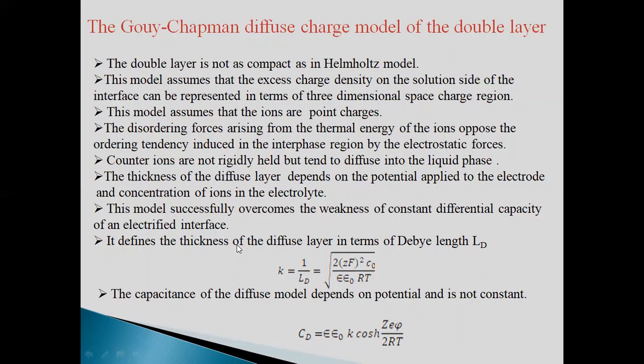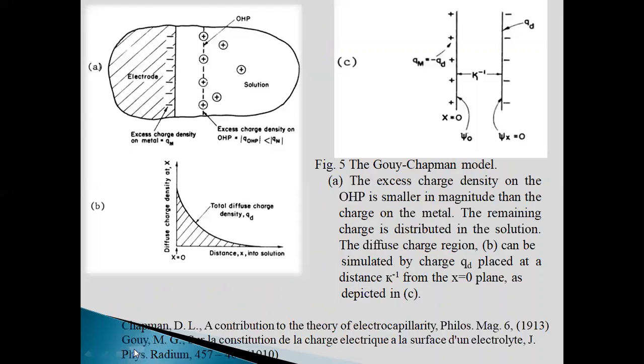So, as shown here, it also tells us about the thickness of the diffuse layer formed in this model, and it is given by the length kappa, which depends on the concentration of ions. So the capacitance is not independent of potential and the concentration of ions according to the Gouy-Chapman model. As shown here, the ions are diffused in the bulk of the solution. They are not fixed due to the electrostatic force of attraction as they are feeling due to the surface of the electrode. The charge of the ions present in the solution and that of the metal electrode is not equal and opposite to each other. So we can see the variation of potential is not linear here. It is an exponential variation of potential that can be shown here.